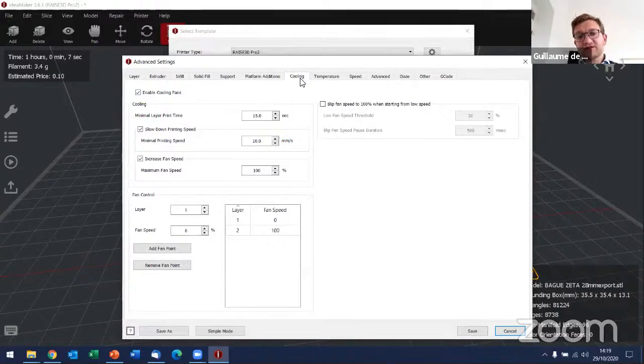Cooling, this is really something critical. The way the technology works is that you actually melt the plastic by pushing it through a heated nozzle. But once it's melted and deposited, you want it to cool down as fast as possible. And this is ensured by small ventilators that will blow fresh air just outside of the nozzle. And here you can decide how strongly you blow air. Basically, it's pretty simple. With ceramic and metal, we usually just cool as much as possible. Because of the density of the material, we really need to evacuate heat, and that's usually 100%.